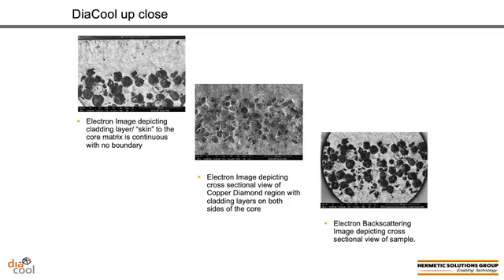Looking from the top down to the lower right, you'll see different cross sections of the material, and different backscattering methodologies that we use to look at the material. In all cases, you can see that there are no boundary layers between that skin and the matrix. It's a very uniform and consistent process that allows that material essentially to blend with the copper diamond matrix. The image you see here in the center just gives us a cross-sectional view of both sides of the substrate so that you can see how effectively the material adheres on both sides of the matrix.